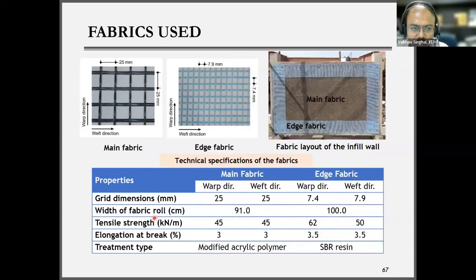So yes, this is the fabric which we have used. So this was the main fabric and this is the edge fabric. The edge fabric was primarily used to make the application of anchors much easier. So you can see the placement of anchors. Anchors were designed in such a way that the anchor should not fail before the failure of the fabric. So the shear strength of these anchors was kept more than the tensile strength of the reinforcing material. Property wise, both fabrics had nearly the same material properties, the same tensile strength. Only the spacings are slightly different. You can see here the main fabric has a spacing of 25 mm and the edge fabric has a spacing of approximately 8 mm.